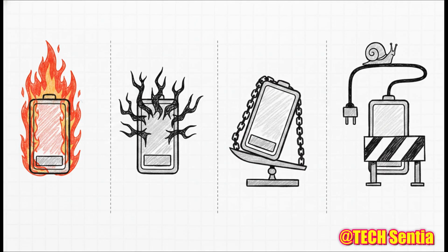First, thermal runaway. These things can start catching fire at just 90 degrees Celsius. That's not even boiling water. Second is that unpredictable dendrite growth we just talked about. Third, the energy density is basically maxed out between 150 and 240 watt-hours per kilogram, which is why EV battery packs are just so unbelievably heavy. And fourth, charging speeds are hard-capped because pushing too much power generates way too much heat.